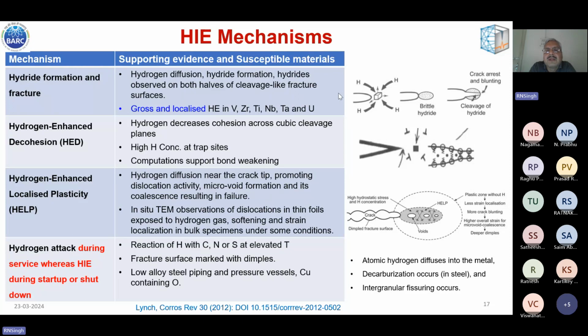So wherever some stress raisers are there, or something which obstructs the dislocation-hydrogen atmosphere movement, there microvoid formation will take place, and then ultimately they will coalesce. And as in the case of normal failure by microvoid coalescence, here also failure will take place. Now this localized plasticity is actually an embrittlement mechanism. What it does is localize the plastic deformation in or near the crack plane itself. That's why the material fails in a brittle manner.